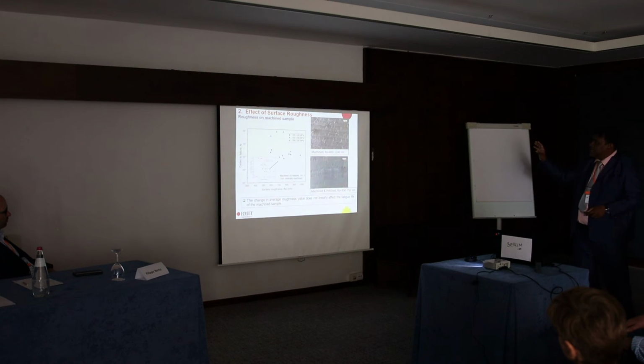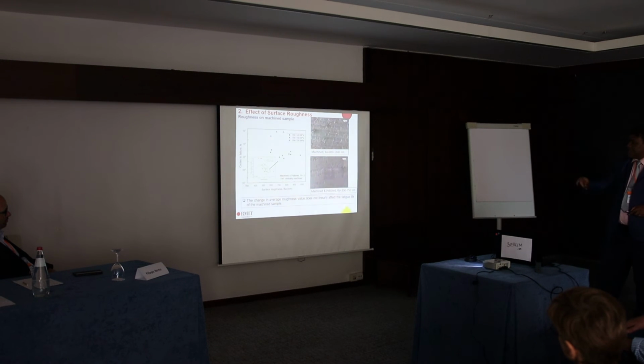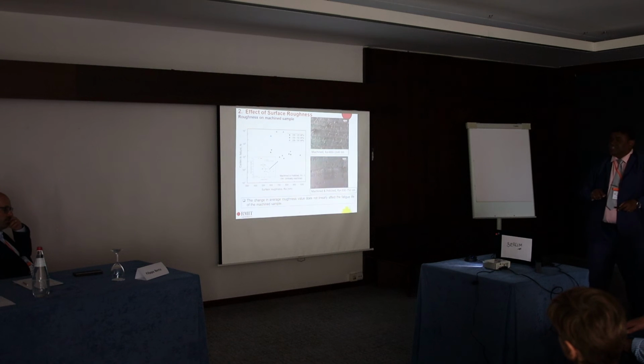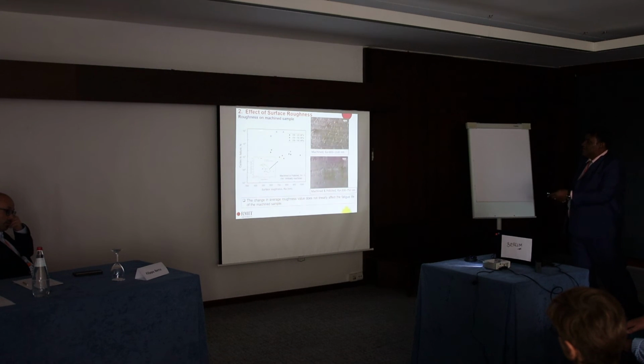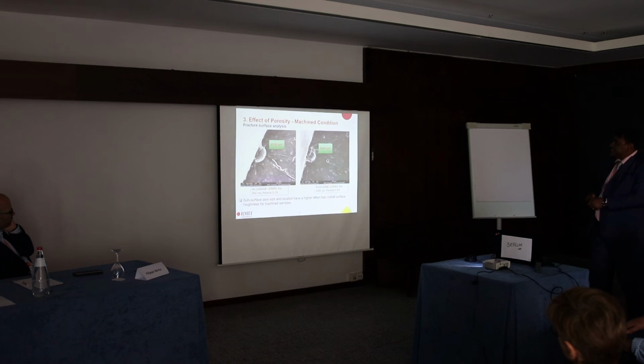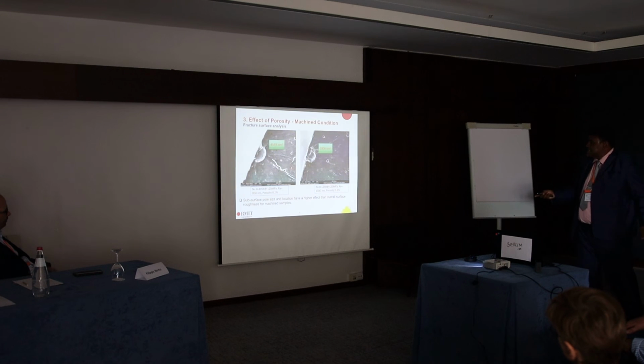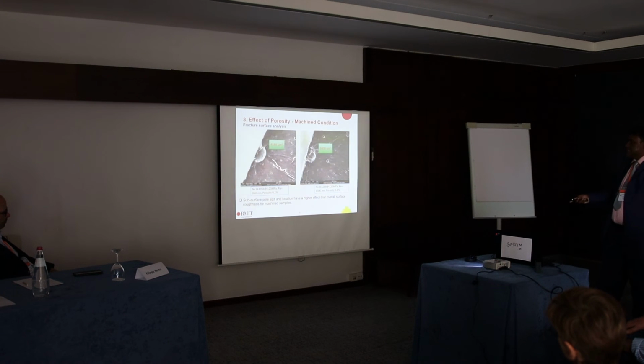Given the time remaining, I will quickly go to surface roughness, which is a key effect. It shows there is no correlation between surface roughness and fatigue, as you see the scatter all over the diagram for all the stress levels for the vertically machined surface. The reason for this is, again, the porosity underlying the surface, which dominates in this case. As you see, in this case, 2 samples with the same porosity but different surface roughness: the much rougher surface has a fatigue life nearly 2 times higher, although the roughness is 1.5 times higher.